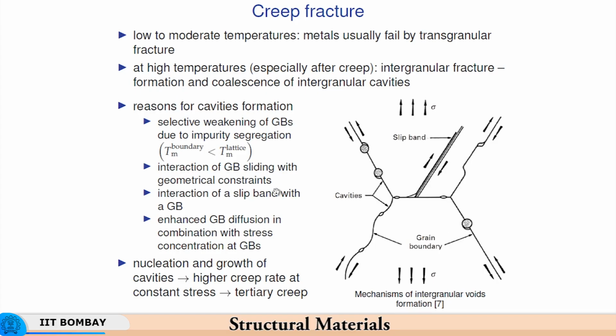Interaction of grain boundary sliding with geometrical constraints is also important, in the sense that geometrical constraints means the constraint of maintaining continuity. Now, if the grain boundary is sliding, then in a polycrystalline material it has got resistances from the neighboring grains as well. That is because they also get affected, and so by virtue of diffusion, the voids or vacancies that are created due to the grain boundary sliding have to be compensated. The lack of material has to be compensated by the diffusion processes. Then you have interaction of slip bands with a grain boundary. So, you have slip bands interacting with the grain boundary, and these slip bands would also therefore alter the shape or profile of the grain boundaries.